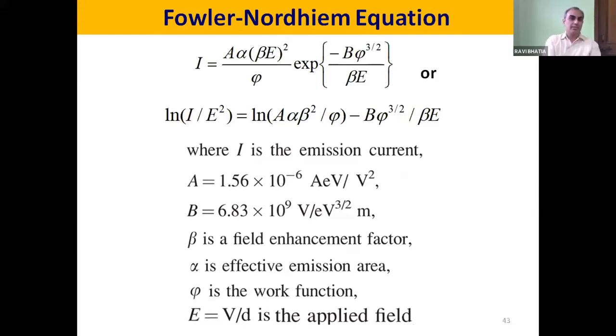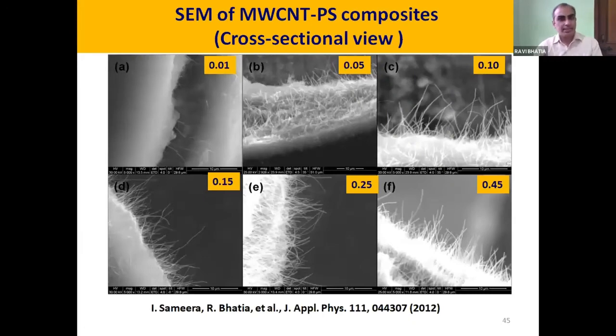If you roughly convert such things, you will see that carbon nanotube can be considered an ideal candidate for field emission work. And because of this beta factor, it is highly desirable that CNTs should be used for field emission studies. But now there is a problem. One should have a vertically aligned carbon nanotube structure, otherwise it won't work. If the orientation of CNTs is in lateral position, the beta value is not going to be improved.